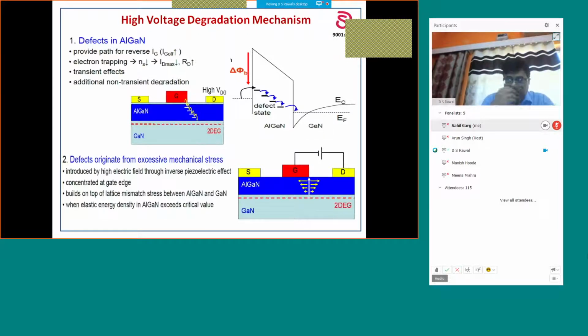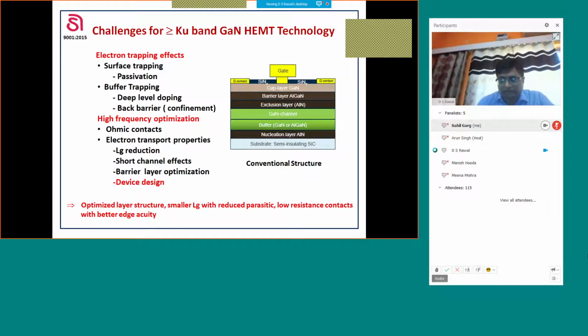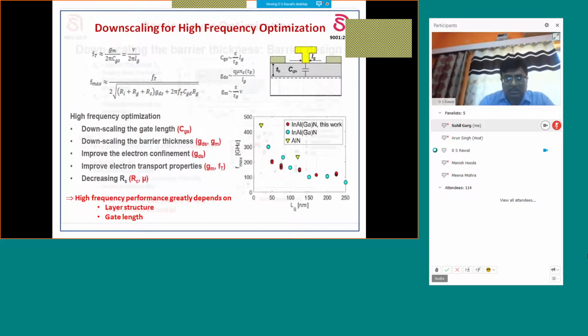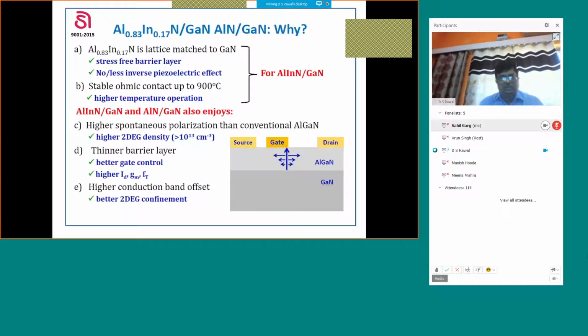So how to take care of this? Now people are going towards a new material system where aluminium indium nitride is used as a barrier layer, because aluminium indium nitride with 17% indium is perfectly lattice matched to gallium nitride. So there is no inverse piezoelectric effect.